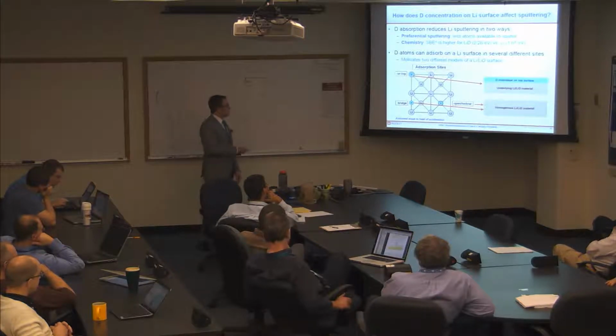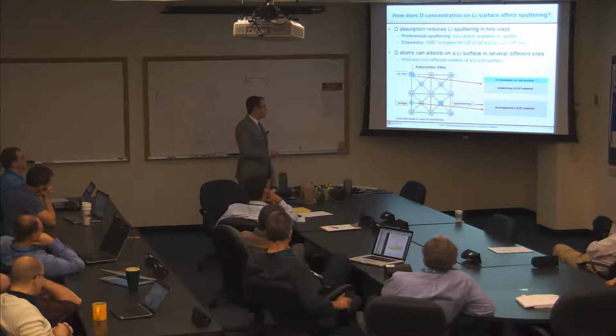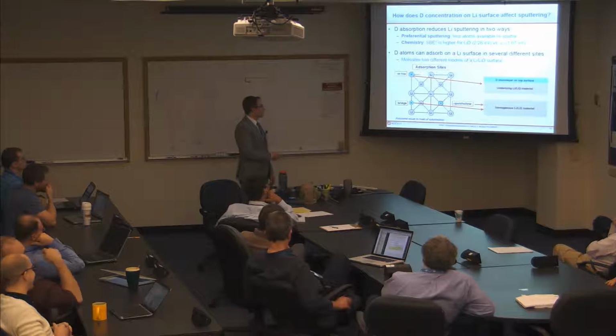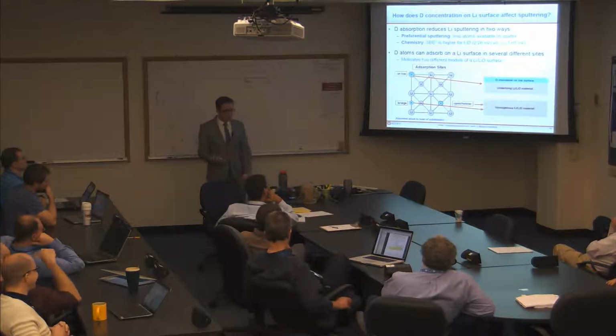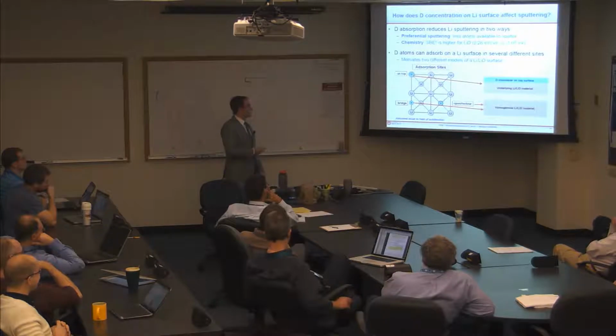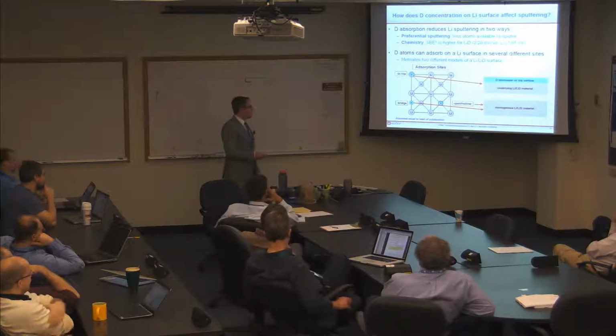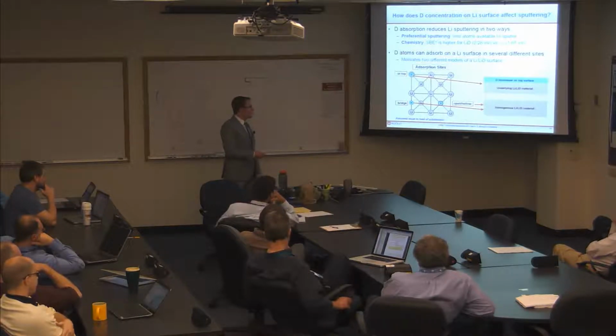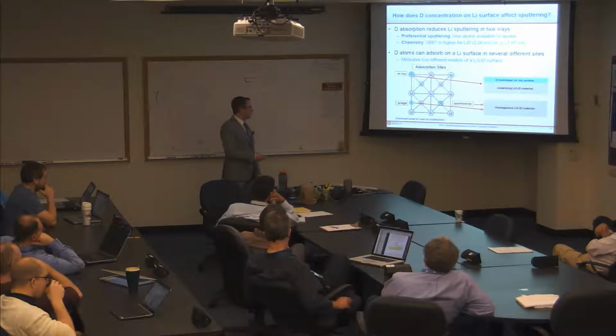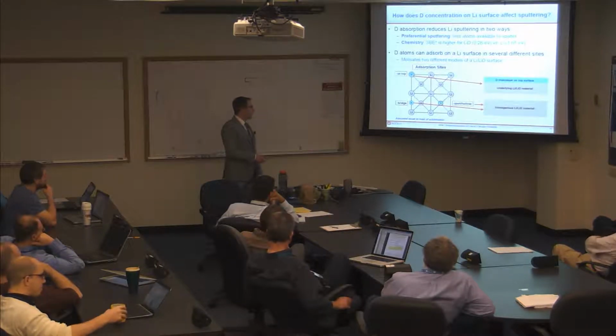And so specifically talking about preferential sputtering now, if you want to look at where the deuterium atoms end up on a lithium surface, we start with the simple case of a lithium lattice, and lithium tends to form a body-centered cubic structure, which you see here. And so you ask, where do the deuterium atoms adsorb when they hit the lithium surface? Well, you can look at various papers, and you see that there are three sites that are energetically favorable. One is on top of a corner lithium atom, one is in the so-called bridge site between two corner lithium atoms, and one is on top of the middle atom of the BCC lattice.